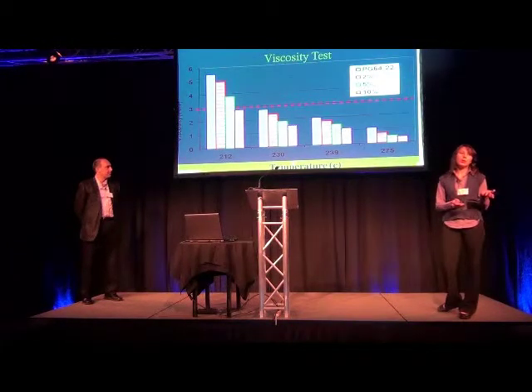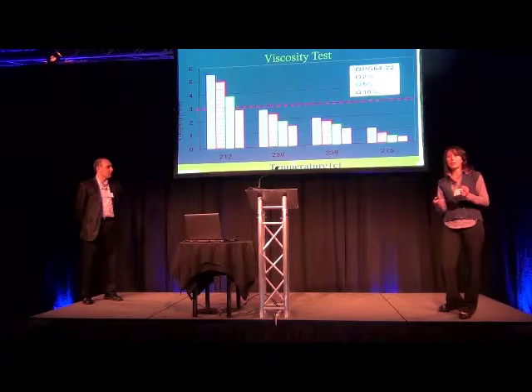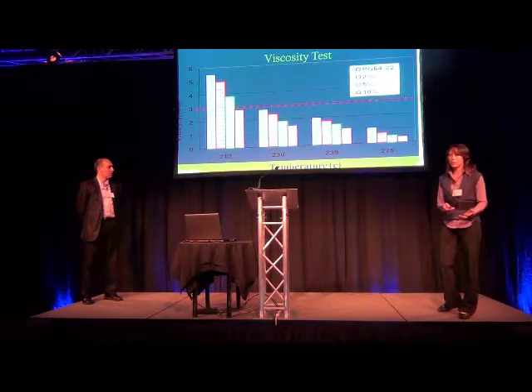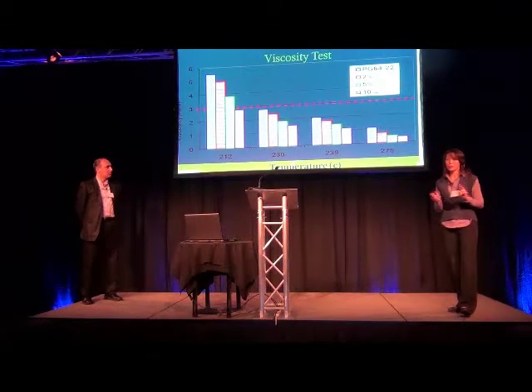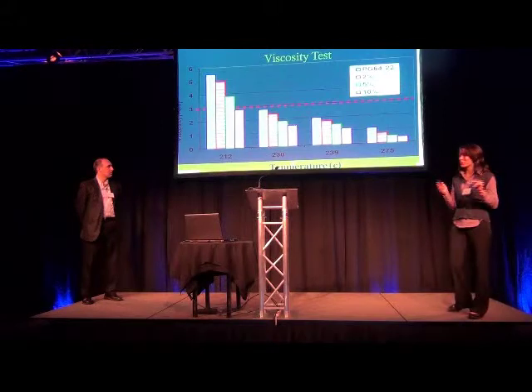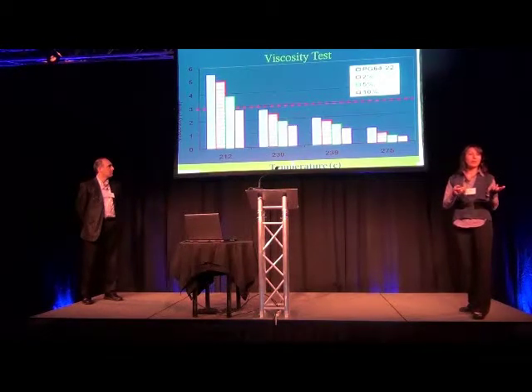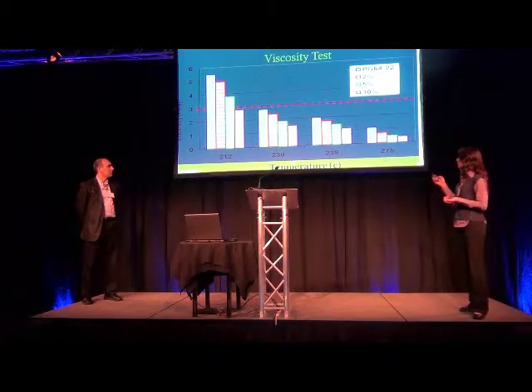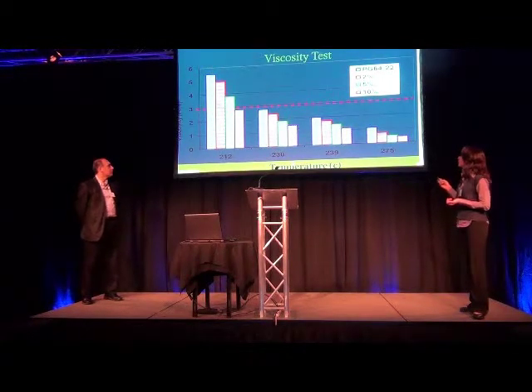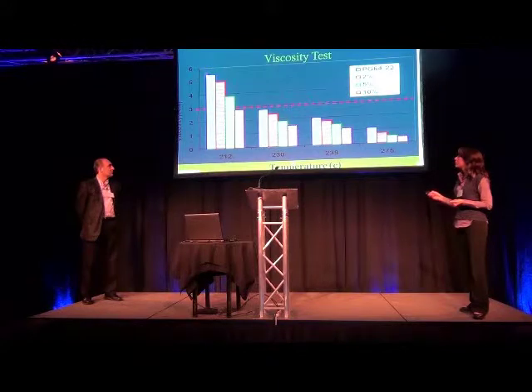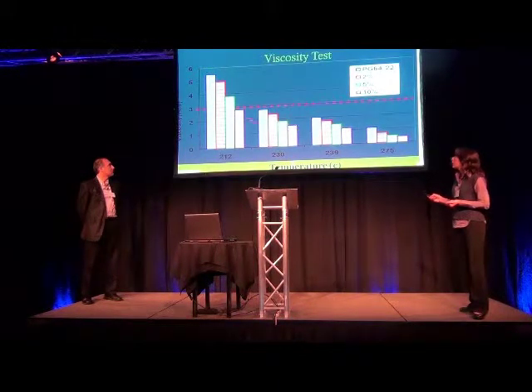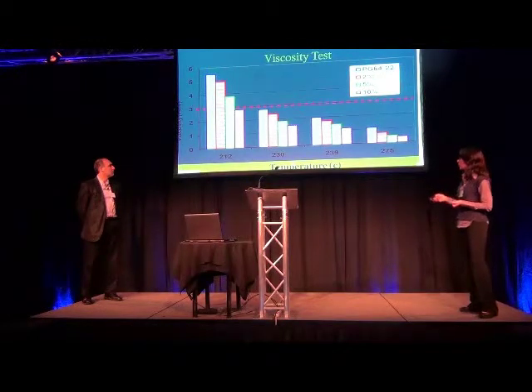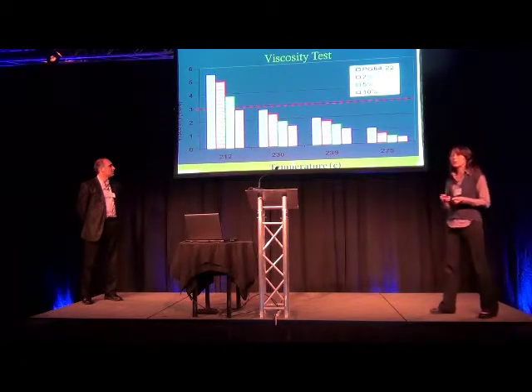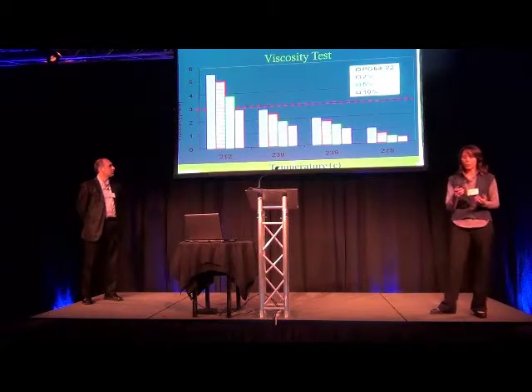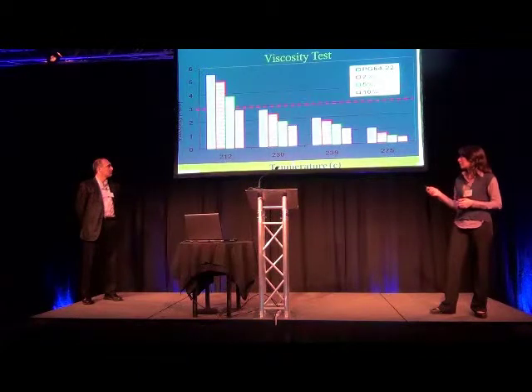And actually, most asphalt producers that we talk to are interested in using a blend instead of a pure non-petroleum-based adhesive. In a way, they just want to keep the name asphalt, because our glue doesn't call itself asphalt, it's PG-grade. So we looked at the blend, and we started with the viscosity test to see how these two materials perform and how the addition of different percentages affects it. With 10%, for example, here you can see the viscosity of our adhesive, and this is a control asphalt, the first column. The viscosity keeps dropping as you increase the percentage at different temperatures, which means it's easier to mix and compact on the road. It's more workable when you have our adhesive in it.